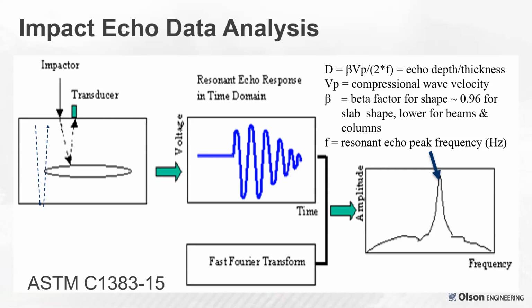There are multiple resonances for beams and columns and other shapes, but when it's a wall-like shape, like slabs, say a tunnel lining, slabs on grade, walls, et cetera, that is generally a single thickness resonant echo peak if there's no damage. If there's cracking at a shallower depth, you'll see a higher frequency echo that corresponds to the shallower depth. And if it's near the surface, you get a resonant echo that's a flexural delamination, as Dennis will talk a little bit about.